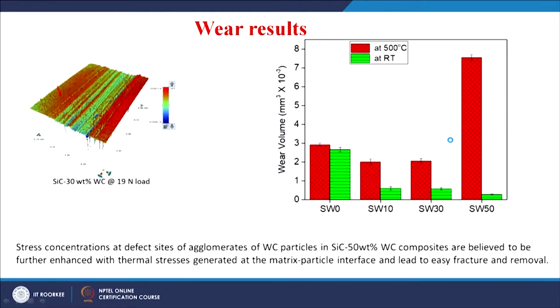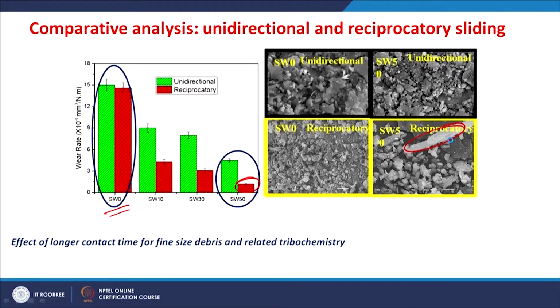So, there is a tribochemistry when the sliding test mode was changed from unidirectional to reciprocatory. In the unidirectional it is a mechanical fracture only, whereas in reciprocatory there is a signature of the tribochemistry involved. If you look at the wear results obtained for these composites tested in unidirectional and reciprocatory sliding conditions, the effect of the longer contact time for the finer size debris leads to this tribochemistry and the resultant wear. So, you get a decrease in the wear.